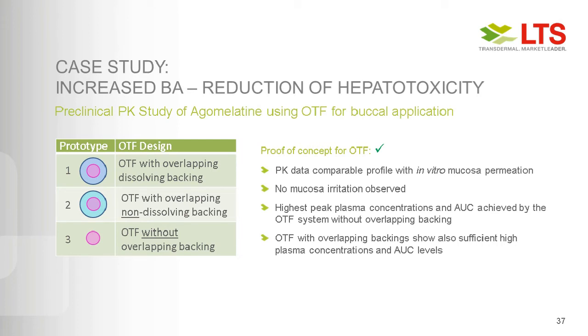The interpretation of this proof of concept study is that we have seen nice PK data which were comparable with the in vitro mucosal permeations based on the systems I showed you before, with this Franz-type of system, especially since it's a pretty static delivery by a buccal patch. We observed no irritation on the mucosal tissues in the mini pigs. The overlapping backing, of course, prevented a high AUC, so the highest AUC was achieved by the film without the backing. But the one with the overlapping backing, which prevents the side effects, showed sufficiently high plasma concentrations, so that the prototype design was feasible, and we could develop an OTF based on this technology.